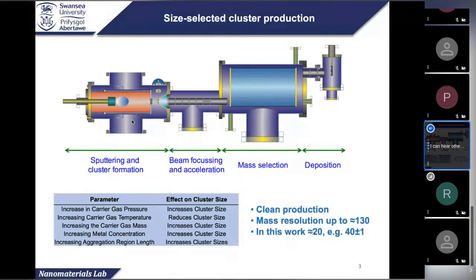Basically it has 4 sections. The first one we call the generation chamber, where the magnetron sputtering and the gas condensation happen. This is a cluster source based on magnetron sputtering, which is a quite widely used technique. You have your metal target mounted on the magnetron head, and you start the sputtering with argon gas or argon plasma, and then you introduce cool helium in the chamber. The atoms or clusters from the sputtering become larger and larger.